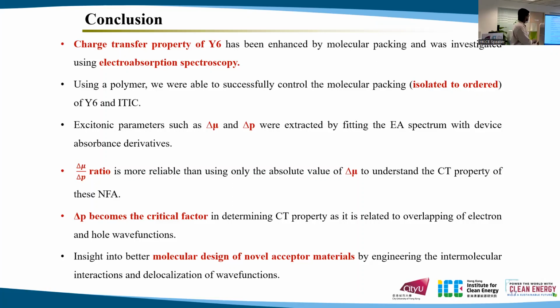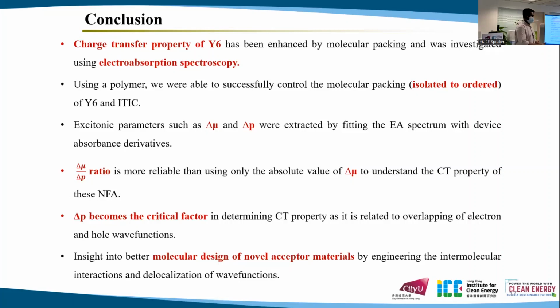We showed that Y6 has strong molecular packing, and it also enhances the CT property of Y6. We used a polymer which can successfully control the molecular packing of Y6 and also ITIC. Then we extracted delta mu and delta p to quantitatively explain the CT properties using the device absorbance derivatives. Delta mu by delta p ratio is more reliable than the absolute value of delta mu to understand the CT properties of these non-fullerene acceptors.